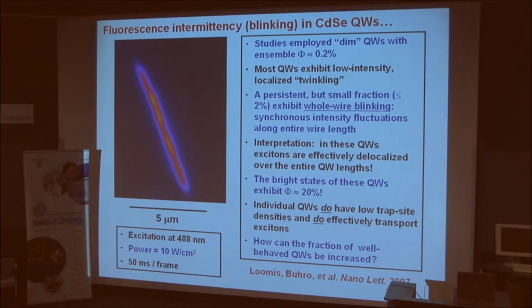And what I'm showing you here is an epifluorescence image of a single cadmium selenide quantum wire. And you can see that it's blinking. And that's really not surprising because individual molecules blink and quantum dots blink. So many things blink. That is, if you continuously irradiate them, they will show fluorescence intensity fluctuations, even as much as on and off. So that's not particularly surprising.